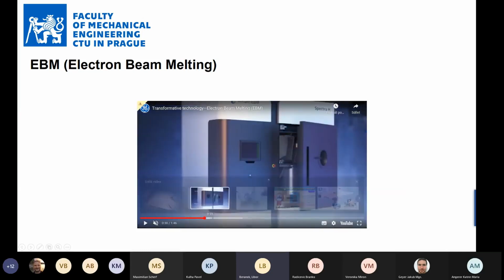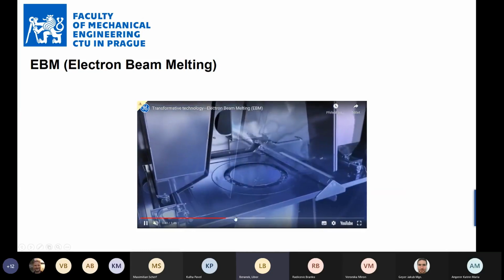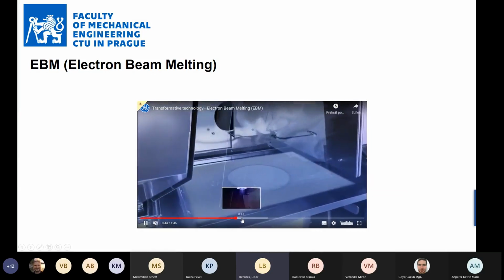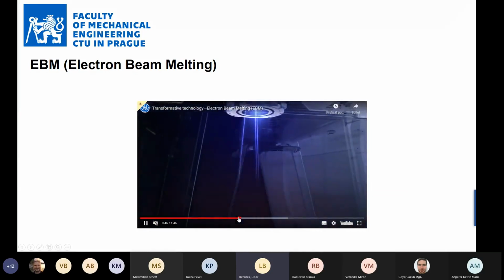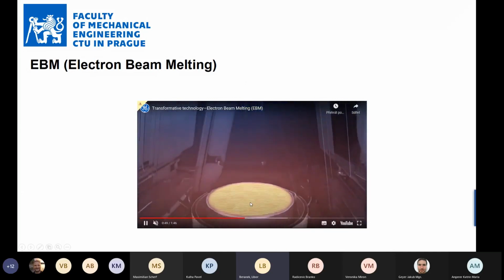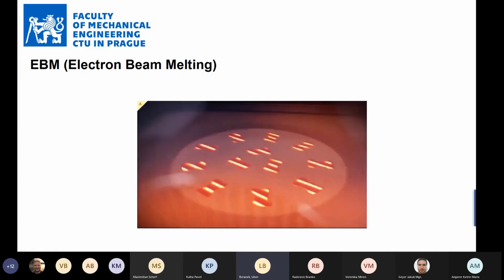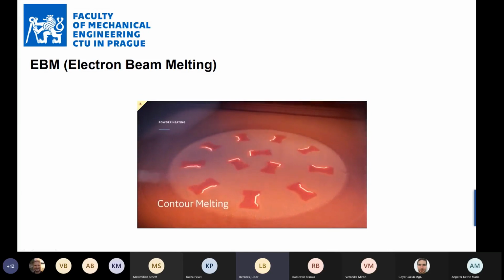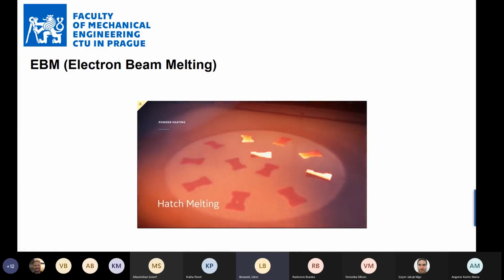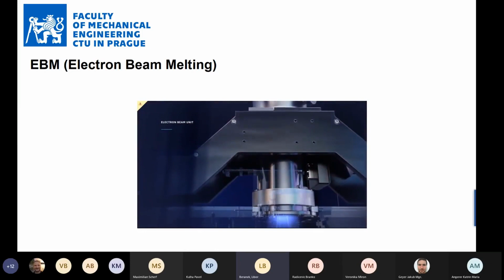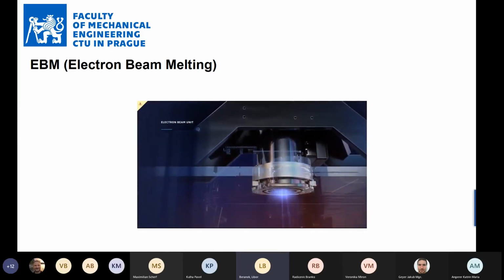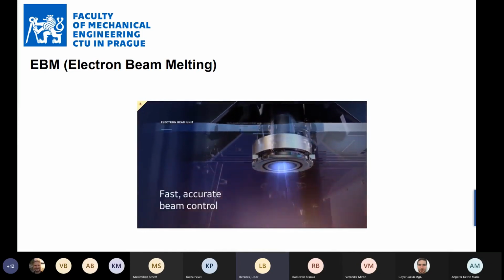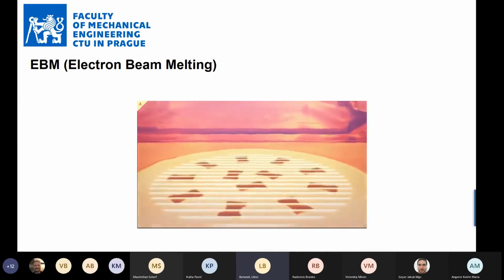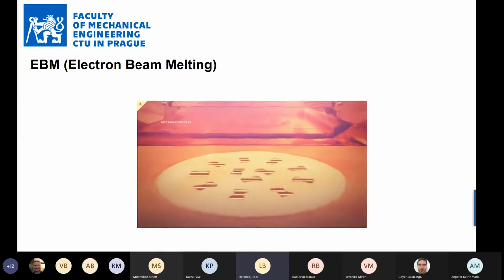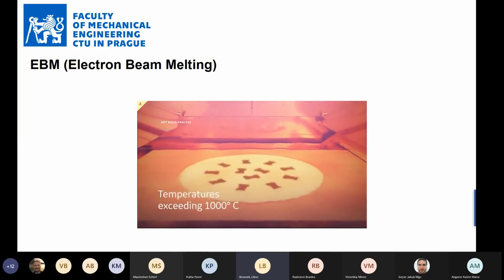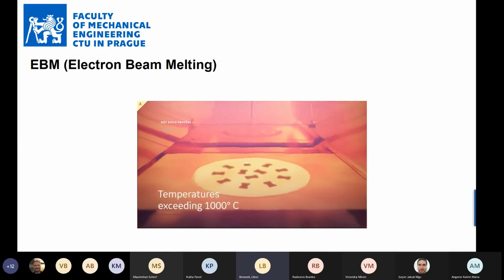But basically, what is a great advantage is that you really have multiple focal points at one time, because it's very easy to split the electron beam using a magnetic field. So you can preheat the whole bed and then do several parts at once. So the technology is very productive. But on the other hand, you are working with vacuum technology. You need to have quite a big vacuum. So the maintenance costs and so on, you have to calculate with those or consider those.